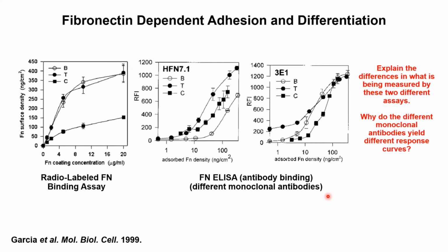Again, we can measure using radioactively labeled proteins the amount of protein on the surface. Here we can see the collagen gel is worse than the polystyrene in terms of its ability to present lots of fibronectin. Both polystyrene surfaces are pretty good, at least in this assay, at absorbing fibronectin.